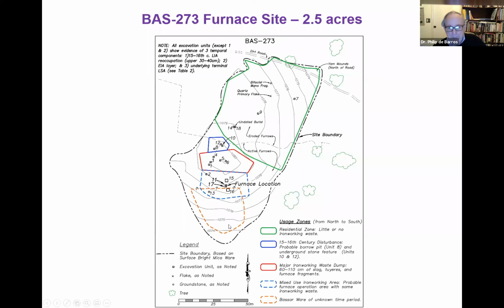And this is a map of the site based on our excavations. I had found this site in 1982 and relocated it and thought maybe we can find a furnace here because it's close to the ore sources. So this was a residential district based on my excavations. Here we found a meter thick of tuyeres, which are the vehicles for putting air from bellows into a furnace or in natural draft furnaces, furnace fragments and lots of slag. So this was a dump.